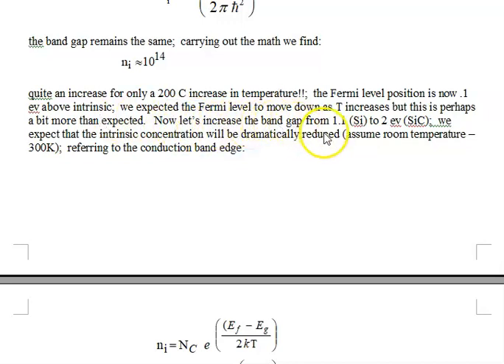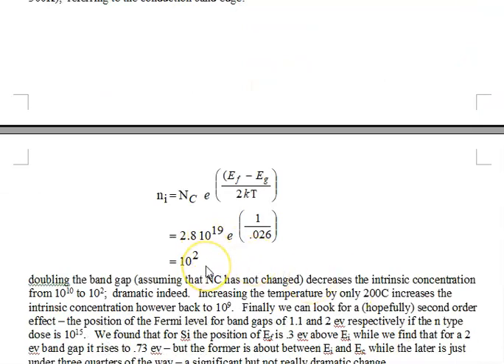Now, let's increase the band gap from 1.1 eV to 2 eV and go back to 300 Kelvin room temperature. Well, higher band gap, we would think that the N sub I goes down, and we can reference it either to the conduction band edge, which we're doing here, or to the intrinsic band edge. Wow, isn't that cool? We find now that the intrinsic concentration decreases from 10 to the 10th to 10 squared, to 100. N sub C doesn't change, not dependent on band gap.